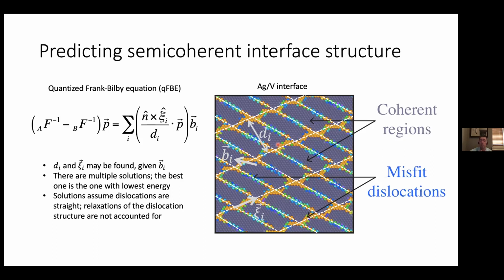One of the nice things about these semi-coherent interfaces is that we can be quantitative about describing the structure, for example, in terms of the spacing between the dislocations found at this interface, their direction with respect to the crystal orientation of the two neighboring grains, and the Burgers vectors of those dislocations. Those are all quantitative ways of describing the structure. And all of these different quantitative features of the interface structure are related through an equation known as the quantized Frank-Bilby equation. I've written it down here on the left.